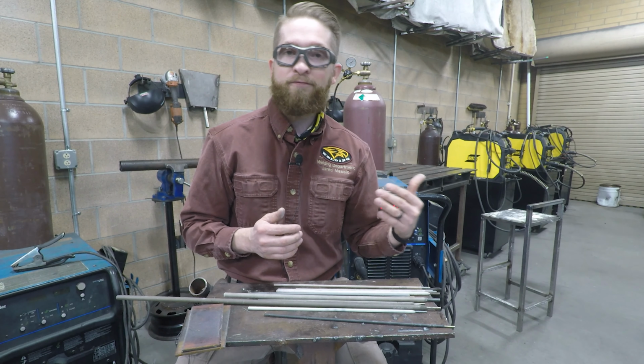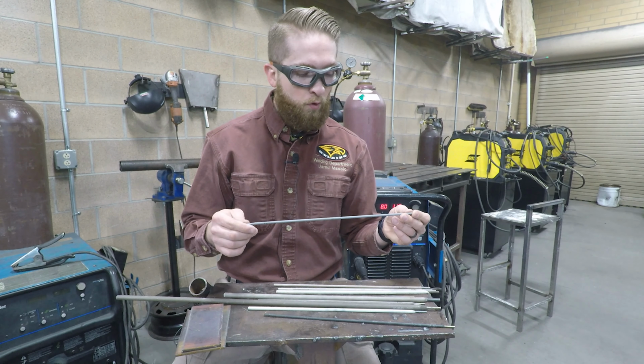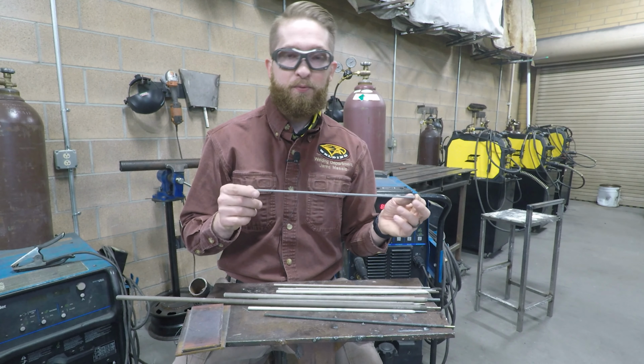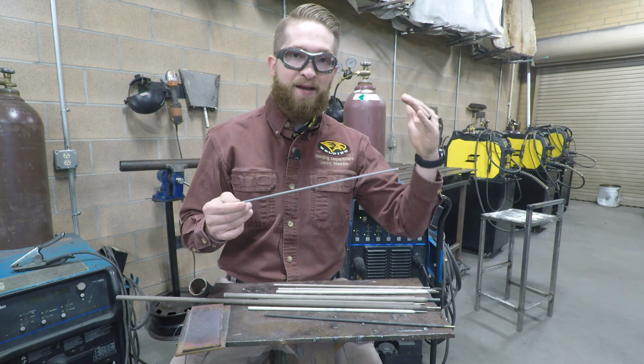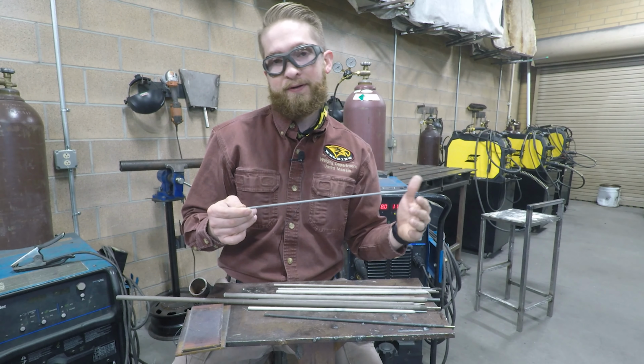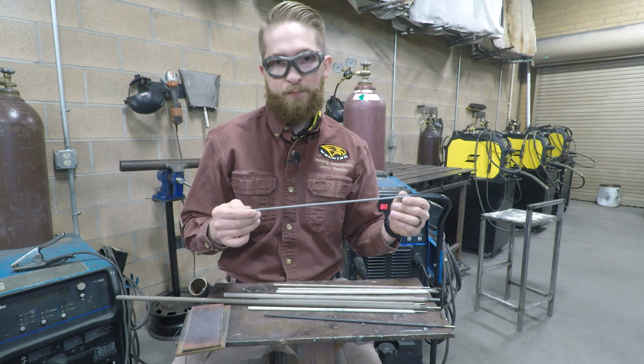We'll see how your travel speed is and how your arc length is, your work angle, and then we will adjust your amperage accordingly. Now when we weld 60-10, 60-10 is a much more aggressive electrode, and when we're going to weld a butt joint with 60-10, we want to go no more than about 90 amps. We'll actually mess around with your amperage quite a bit with 60-10. At the max end, 90, but maybe we'll go all the way down to like 75, depending on your welding ability and also your electrode control.